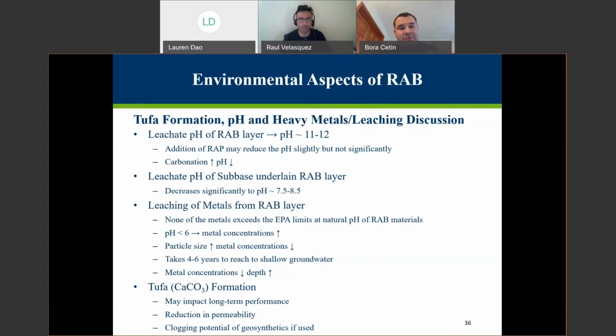And whatever leaches from the base layer goes to the sub-base or base layer, and our research studies show that once the leachate from the recycled aggregate base layer has leached through the sub-base or base layer, your effluent pH beneath that sub-base or subgrade is 7.5 to 8.5, even lower than that. So in terms of environmental concerns, high pH is not really a concern, because the sub-base and subgrade layers underneath the RAB layer disperse and dissipate that high pH value within themselves.